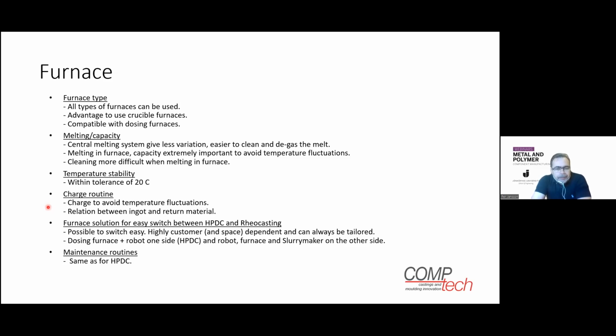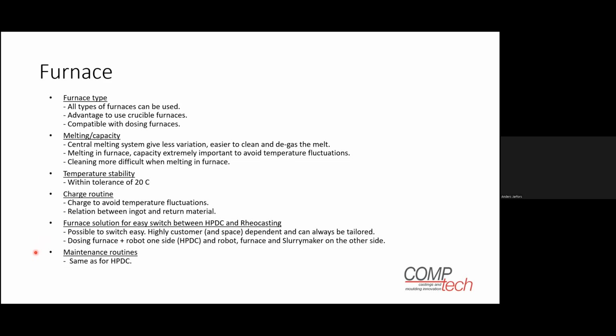Then we have one advantage with this: in the same installation you can cast both with Rheocasting and also conventional liquid casting, conventional high pressure die casting. One thing that is important is that you need to switch the alloy between the two processes. Usually in high pressure die casting you are using eutectic alloys, and in Rheocasting we cannot use the eutectic alloys, and therefore you need to change the alloy.